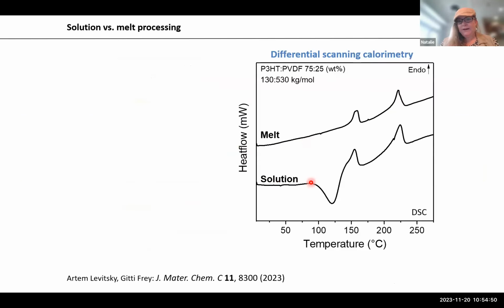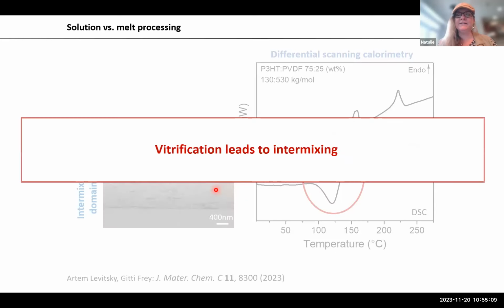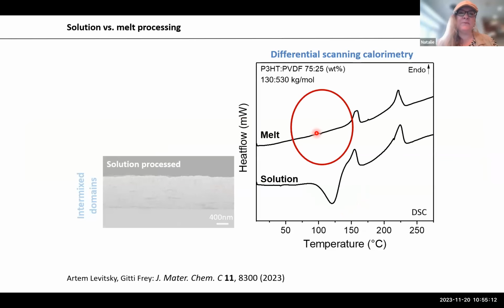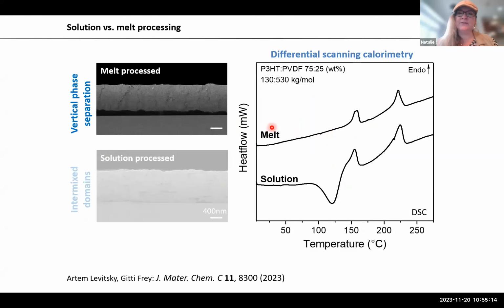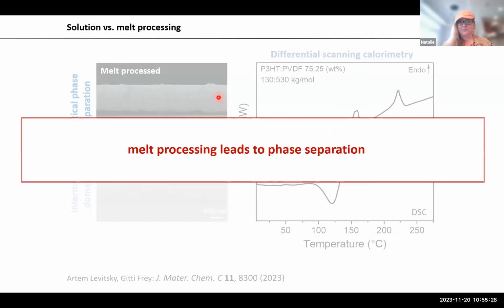And you really immediately see the solutions are where you have one co-solvent. It's really critical. If you measure thermal analysis, you observe an exotherm, meaning at the beginning you had something pretty amorphous, molecularly disordered, but intermixed. In the melt, you see this didn't happen. So it means you already have phase separation, and they lead to these two endotherms, the melting of PVDF and melting of P3HT. And here you see the PVDF is this dark black layer, P3HT rich is on top.